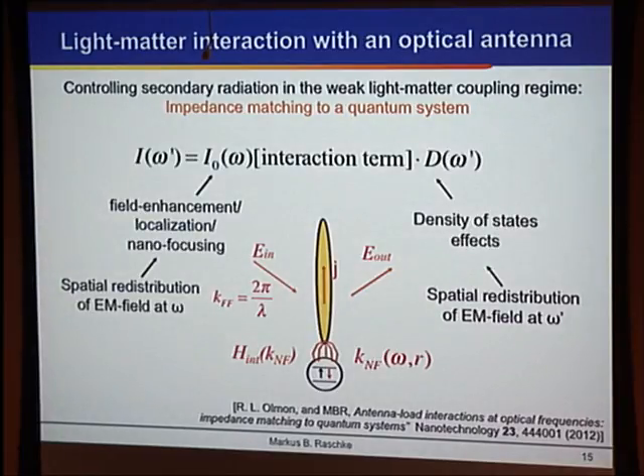So this is really the microscopic picture of the function of the system, and this is why we actually get an increase in sensitivity with increase in spatial resolution. This is a highly non-trivial concept and one of the key issues in microscopy or imaging science in general, because the higher you make your spatial resolution normally, you're probing less and less material. And so you're losing sensitivity as you increase spatial resolution. But here we are actually gaining sensitivity as we go to higher and higher spatial resolution.